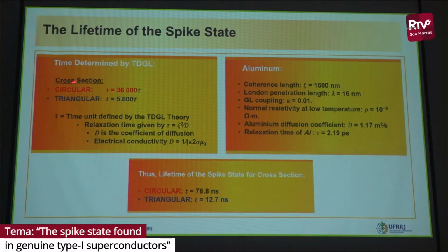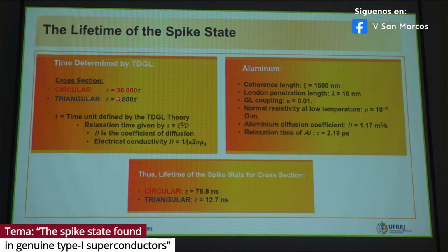For circular cross section, the relaxation time, by my calculations using finite element method, is 36,000 tau, and for triangular is 5,800 tau. What is tau? Tau is the unit of time in the Ginzburg-Landau theory. D is the coefficient of diffusion, in this case for aluminum. Electrical conductivity, D is the electrical conductivity.